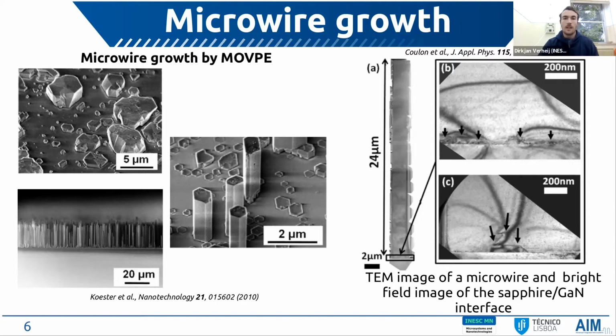grown by metal organic vapor phase epitaxy. And in a very simplistic way, these wires are grown like this. First, small islands are grown on a sapphire substrate, as you can see here. And then the growth conditions are such that especially the vertical growth is stimulated. So instead of growing laterally, the wires grow only in the vertical direction. And in the end, we obtain an entire forest of microwires in the vertical direction.